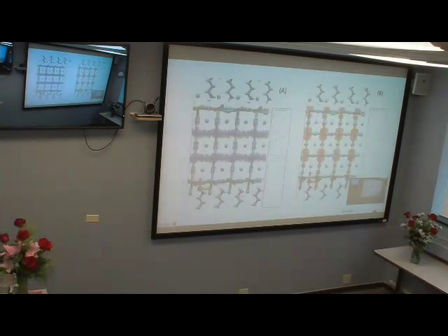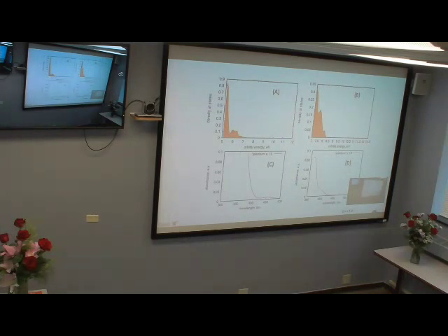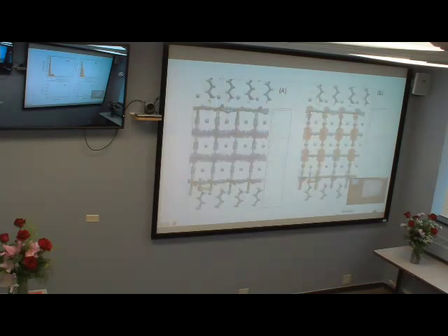That corresponds to the one with the larger band gap, B. So the larger band gap has HOMO-LUMO orbitals located on this intermediate layer, connecting inorganic atoms between the unit cells, the iodine and cesium layer.